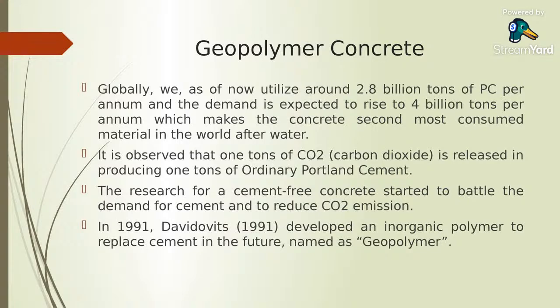We know that around 2.8 billion tons of Portland cement is used around the world, and it's not 4 billion. Actually, it is 40 billion tons per annum that will be used. It is expected to rise up to 14 billion tons per annum. So it makes concrete the second most consumed material in the world after water. So we can see how hugely concrete is being used in this world. Okay, and we also know that for 1 kg of cement, almost 1 kg of carbon dioxide is emitted. So we can see how much carbon footprint there is for cement production and for concrete production.